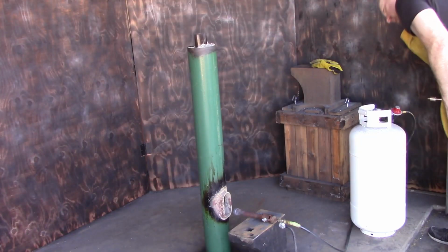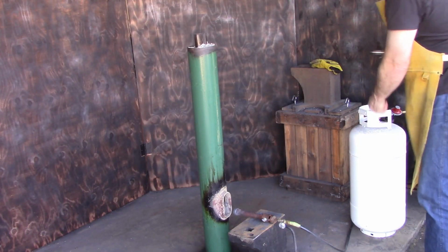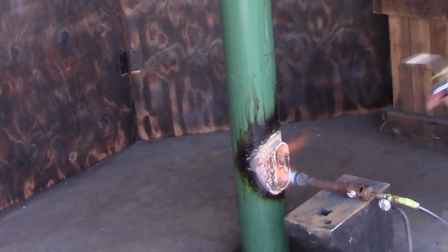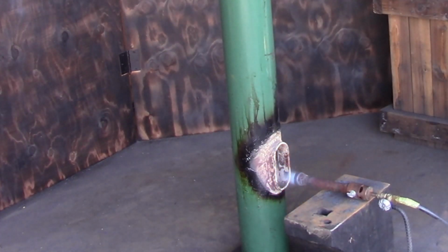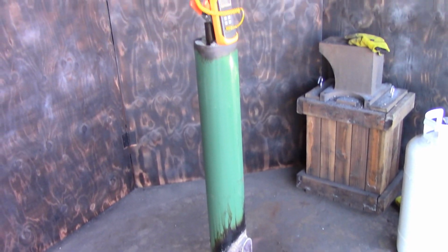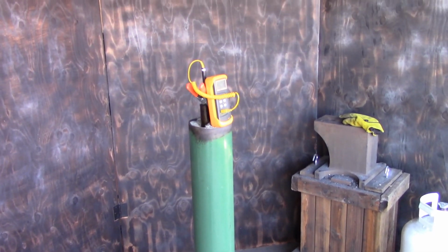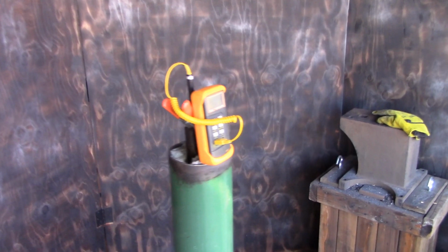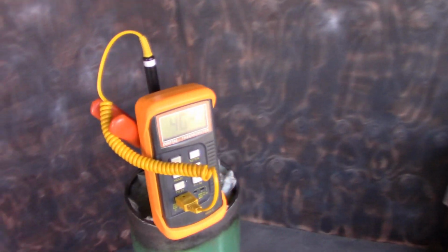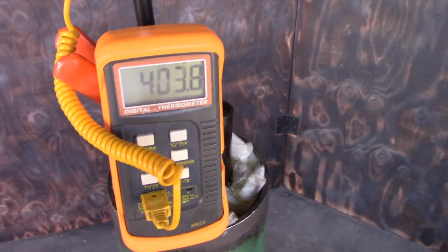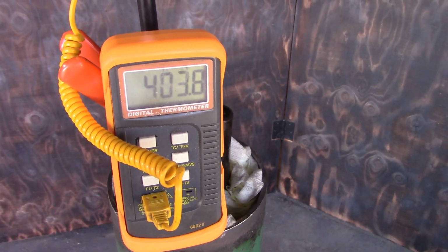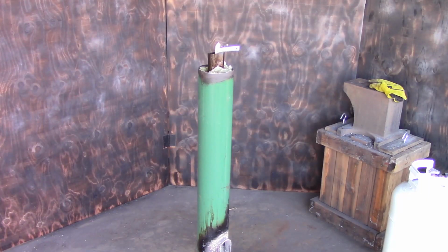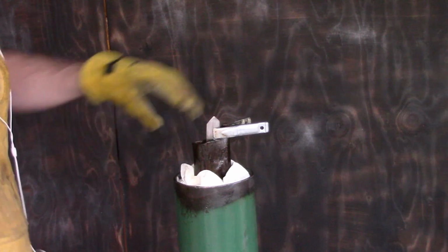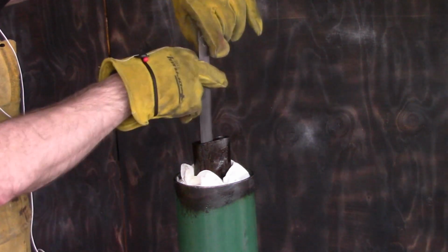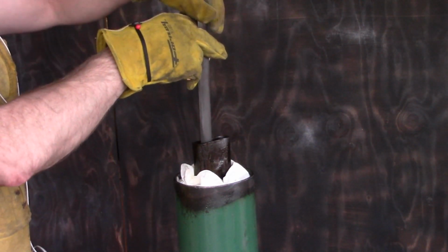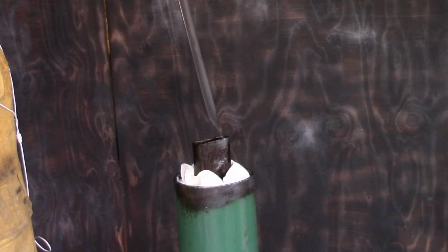For tempering my blades, I use a hot oil bath. I like this method because I can control the temperature very tightly to within just a couple degrees. Once the oil reaches 400 degrees Fahrenheit, I immerse the blade and leave it for 1 hour. After 1 hour, I remove the blade, and though I don't show it in this video, while the blade is still hot from the oil bath, I gently straighten out any lateral warping.